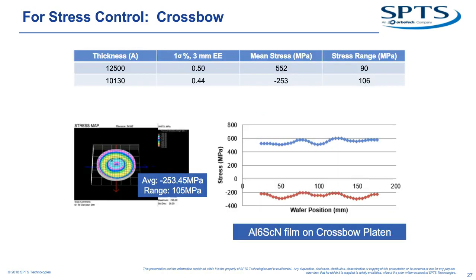Stress control is different. For stress control, we have some new hardware called the crossbow platen. The crossbow works in the compressive and in the tensile range. You can see on here, we have the mean stress of the film was 550 megapascal or minus 250 megapascal compressive, but in both cases, we have a stress range of around 100 megapascal across an 8-inch wafer. This is something like 2 times better than our nearest competitor. And at the same time, we have thickness control. The thickness uniformity has not been affected. 0.5%, 1 sigma on an 8-inch wafer.